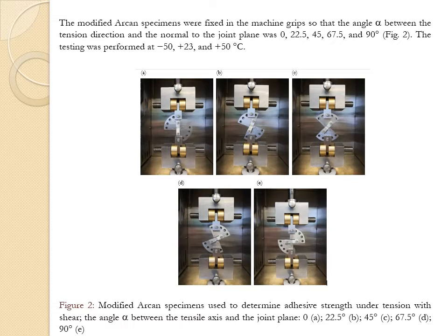The testing was performed at -50, plus 23, and plus 50 degrees C. The force P and the relative displacement of the specimen halves along the loading direction during the testing were measured by a dynamometer and an extensometer complementing the testing machine.